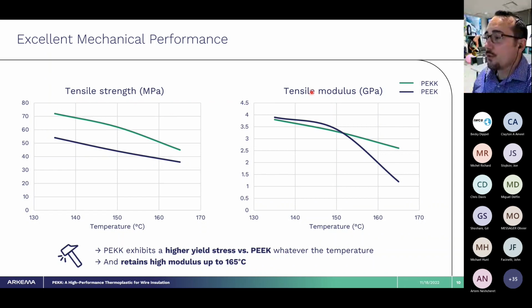The same thing is going to be true for the tensile modulus. At about the 160 mark or so, you're going to see the PEEK dropping, while the PEKK is going to retain its modulus for a longer duration at those higher temperatures. Again, because of that high temperature performance of the material, we're going to retain these properties.